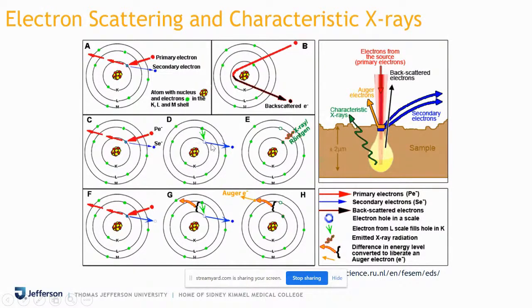There is a void created in the figure D. So the arrow shows that the nearest L shell has an electron which jumps into the K shell to fill up this void. As a result of this, to make it a stable electronic structure, the jumping of these electrons between the shells leads to an emission of photon or energy, and this energy or photon is called X-rays or the characteristic X-rays.